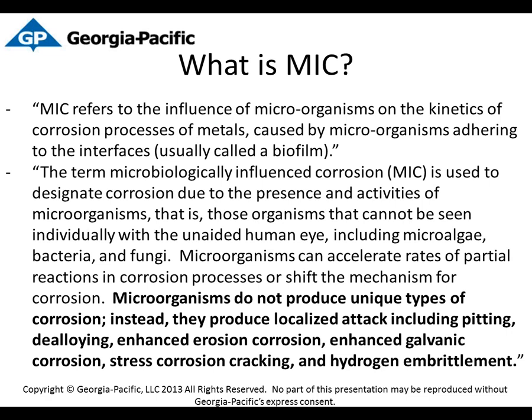So microorganisms do not produce unique types of corrosion. Instead, they produce localized attack, including pitting, dealloying, enhanced erosion corrosion, enhanced galvanic corrosion, stress corrosion cracking, and hydrogen embrittlement. And I'm going to make another point here. The stress corrosion cracking, that tripped us up in the beginning. The first time I ever heard about MIC was in 2012. It was in one of our bleach plants where we had high chloride environments, and we were using 6 moly stainless steel, a super austenitic alloy, AL6XN, that was specifically chosen for the high chloride environments, but we started seeing leaks in the piping. And we would send samples out, and the metallurgist kept coming back saying it's chloride attack and stress corrosion cracking, chloride pitting.